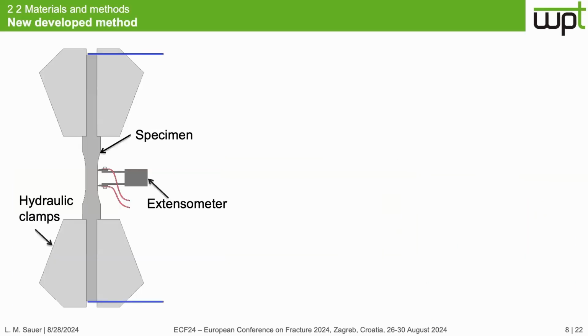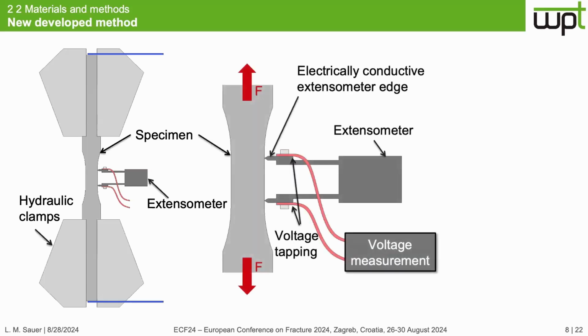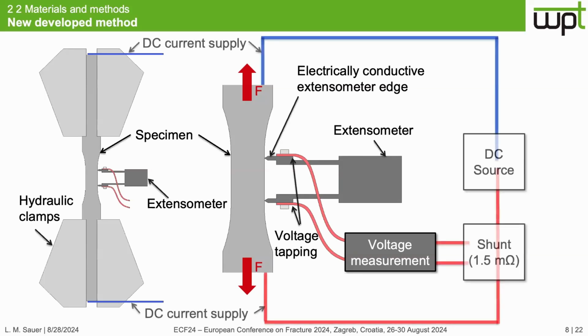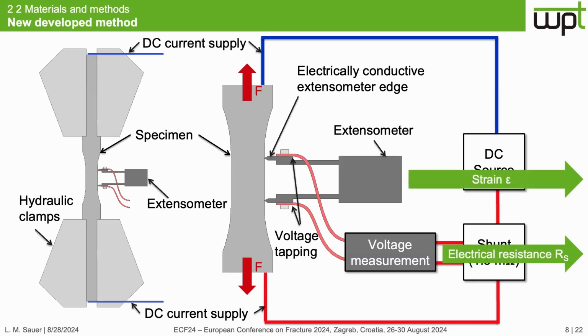And for the electrical resistance measurement, a new method was developed by combining the strain measurement via extensometer with the electrical resistance measurement. For this purpose, the electrically conductive extensometer edges were connected with cables to the voltage measurement, so that the electrical resistance can be measured at the same location where the strain was measured, so that they can be combined. And the DC current was introduced through the hydraulic clamps and measured with another voltage measurement over a shunt with a defined electrical resistance. As a result, the electrical resistance and the strain can be measured at the same location, so that the strain can directly be transferred to the length change of the electrical resistance during the fatigue test.